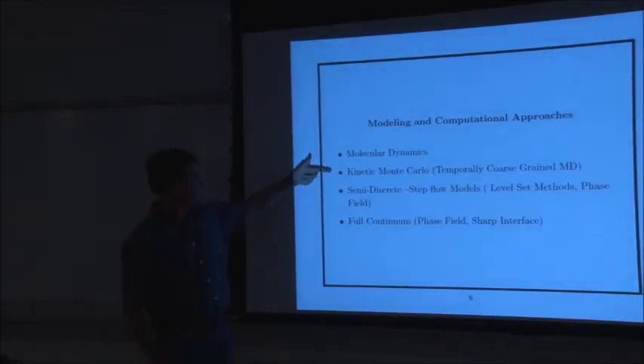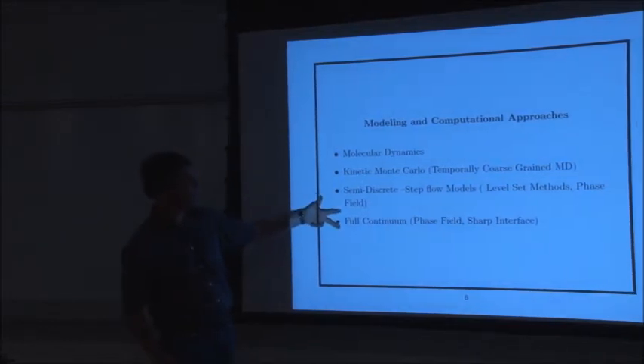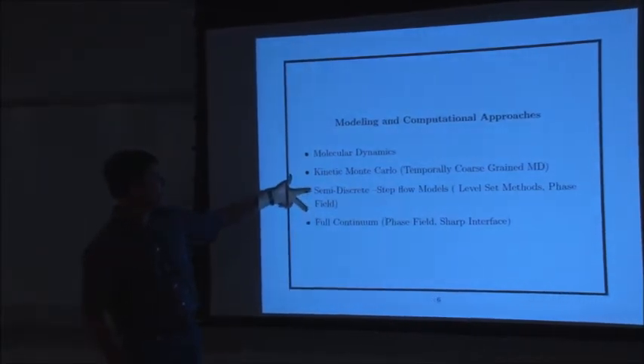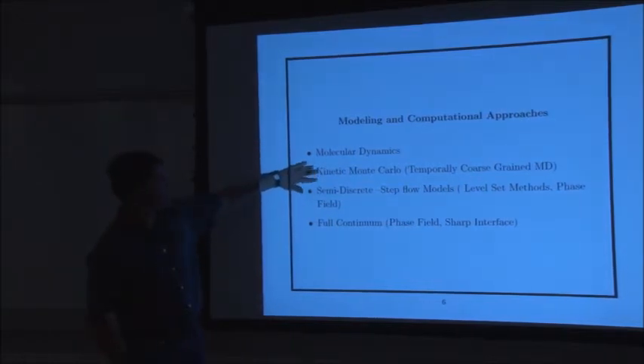At this point in science, from a modeling point of view, these are our choices. You can resort to molecular dynamics, which is very difficult. You can go all the way to full continuum models, though lots of physics is hard to incorporate and many times it gets the wrong physics. There are other continuum-like methods with some advantages. But I think kinetic Monte Carlo is ideally suited because it's exactly between these — it has enough physics that we can get a good idea of what's happening, yet it's still tractable enough to do simulations on length and time scales relevant for experiments.